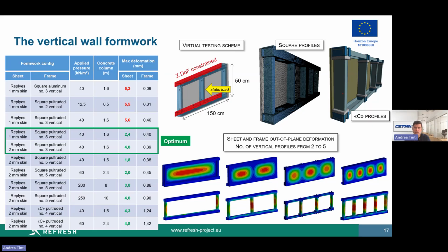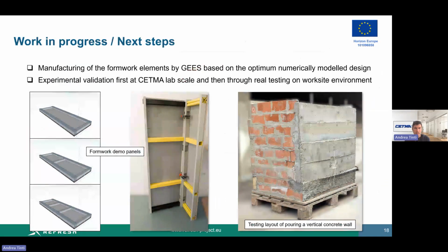For the frame, both traditional aluminium and commercial pultruded profiles were evaluated in different number and geometries. Then, to model the process of concrete pouring, a static pressure was applied normally, corresponding to a fresh concrete column of variable height, and the out-of-plane deformation was numerically measured, mostly affecting the sheet rather than the rigid frame that always resulted quite unaffected. So in the end, virtual testing allowed to optimize the constructive parameters to get the required performance, basically the permitted pressure and deformation.